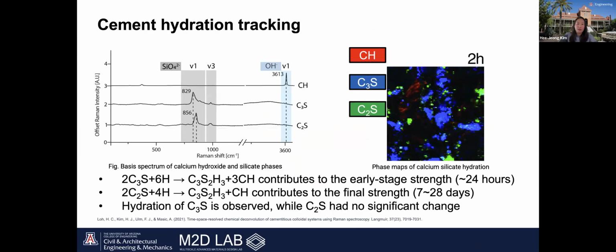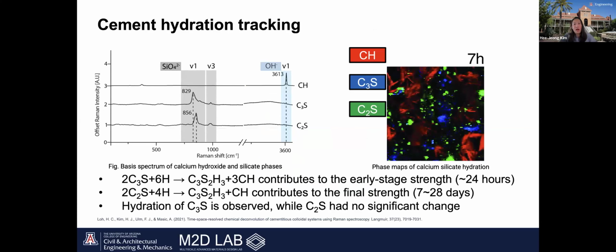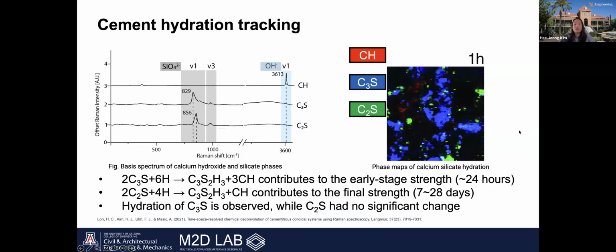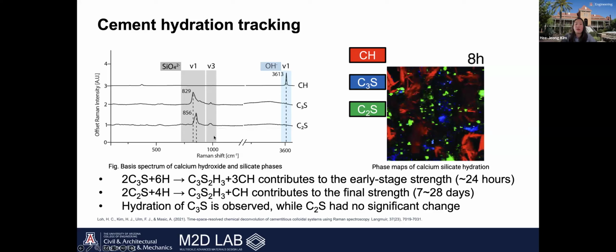And by using this technique, we can map the Raman images and track the hydration process of calcium silicate in situ over a 24-hour period. You can see the time lapse of this process in the video on the right over here. And the Raman spectra used for this mapping, including those of calcium hydroxide and silicate phases, are shown in the figure on the left.